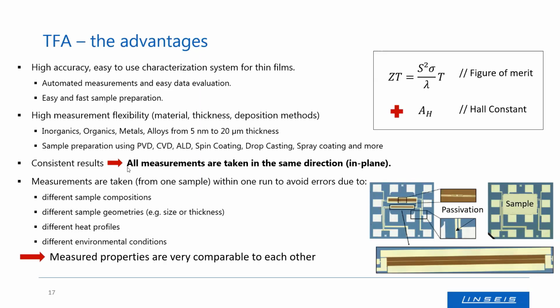All measurements of all parameters are taken in the same direction, in the plane of the thin film. And this is very important because we saw on a previous slide that thin films are highly anisotropic, and you should measure all the properties in the same direction. And as all measurements are taken on the same sample deposited on the chip, you avoid errors due to different sample compositions or sample geometries, or due to different environmental conditions like different heat profiles. So you can really compare all the results to each other because they are measured on the same sample under the same conditions.